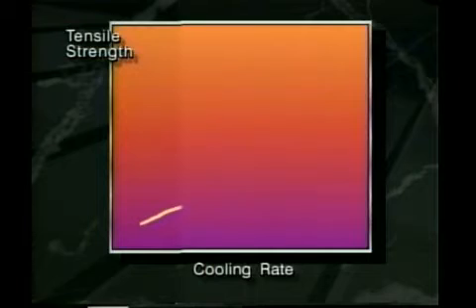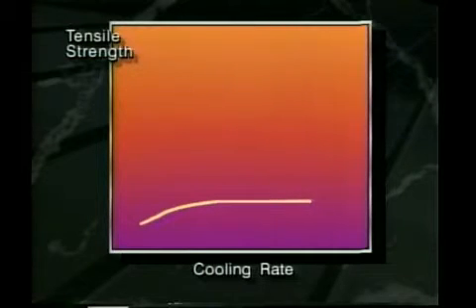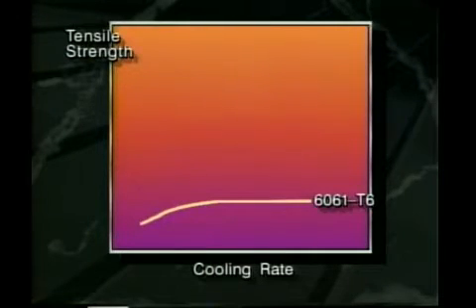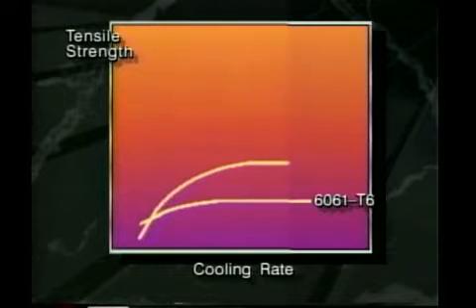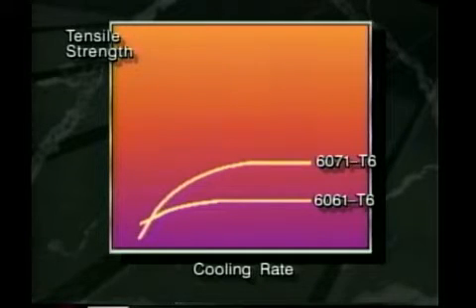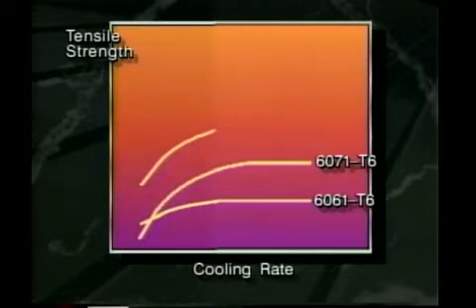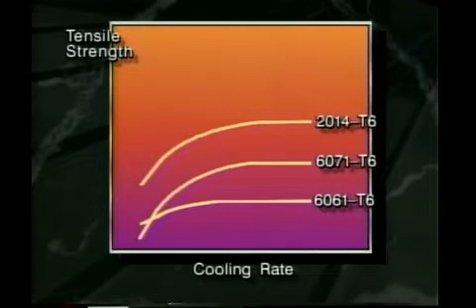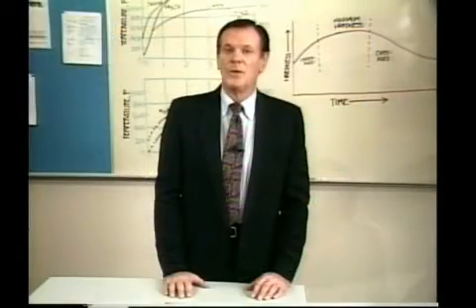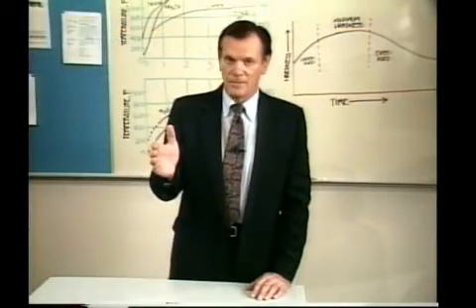The answers to our questions, how fast must the parts be quenched, and what is the quench sensitivity for different alloys, are given in the following chart. To determine the quench sensitivity of different alloys, Alcoa quenched different alloys in various quenchants that produced different quenching rates. The resulting tensile strengths were then plotted against the measured quench rate through the 750 to 550 degree critical range, which was determined in the previous chart.